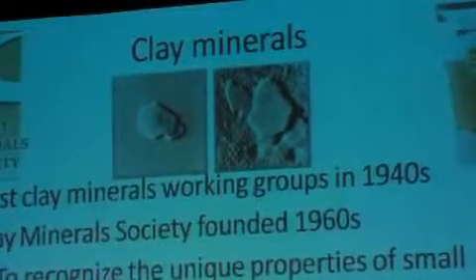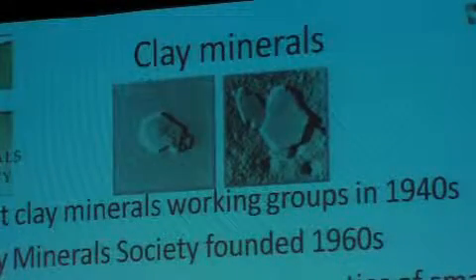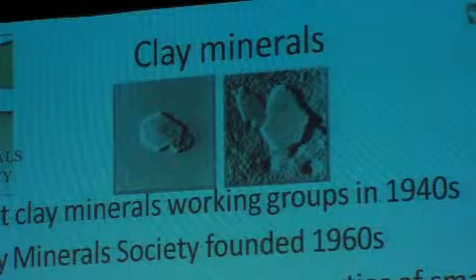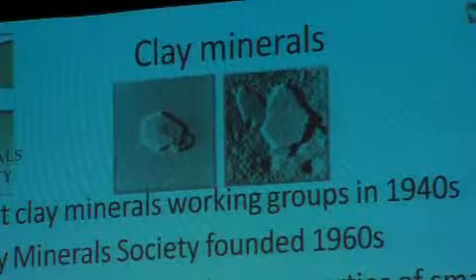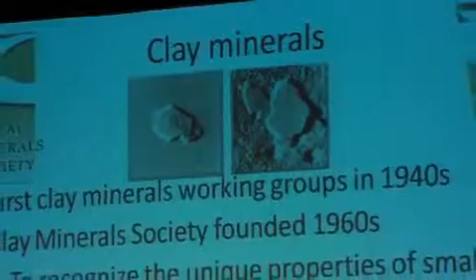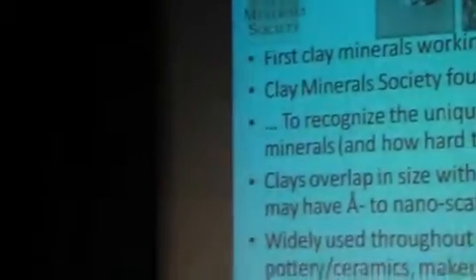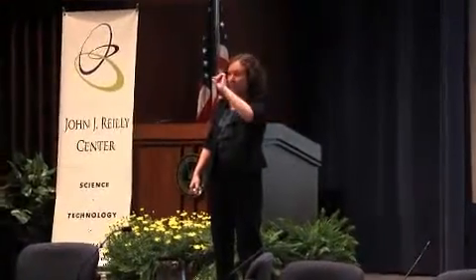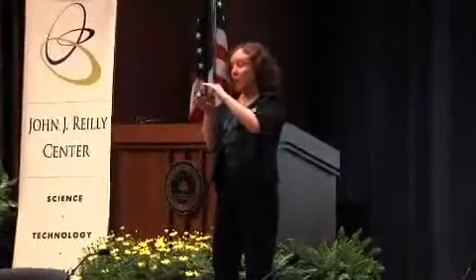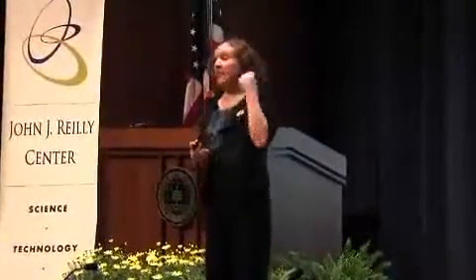Any of you in here who've ever done atomic force microscopy: when I was a student at Stanford, I opened up the first one that was ever sold by Digital Instruments. And they didn't have any way of calibrating the height that you were measuring with the AFM. We worked very closely with them, since we knew what the spacings of steps should be on this clay and on mica, and we were able to use that for them to calibrate the heights. So it was the mineral nanoparticles and nanoscale structures on minerals that allowed AFM to calibrate its first height range down at single angstroms or a few angstroms.